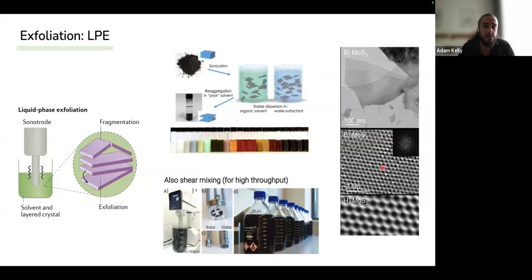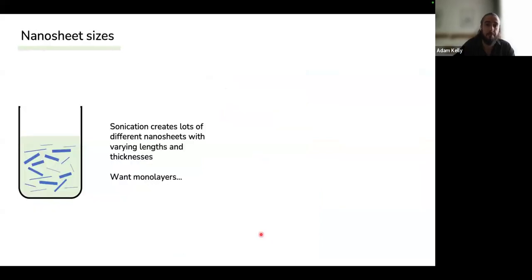Now, this technique is also scalable. We can use shear mixing then, which allows us to process liters per hour of this. We take a shear mixer, we take our material again, and what this does is that it applies shear effects into your dispersion, and then we can do this on the scale of tens and tens of liters. So this is the commercial process that people generally use for creating large amounts of commercial material.